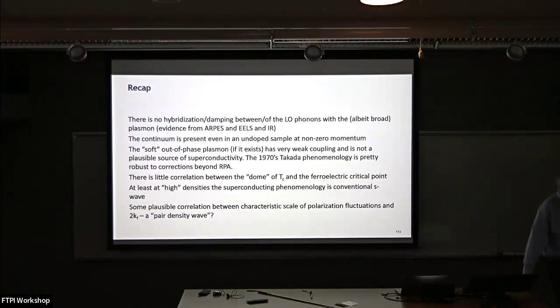Quick question. In the very dilute limit where you have one pocket, what in your mind is the transport scattering mechanism? It looks like an ordinary metal. You have a tiny pocket. Well, here's another conundrum. These are very good metals at low temperature. By the time you hit room temperature, they're very bad metals. That's up to 80, 100 Kelvin. And by the way, there are three materials that do this right now, and they're all on the verge of being ferroelectrics: strontium titanate, potassium tantalate, and tin telluride. They all have basically a T-squared resistivity, so the mobility is dropping very slowly. What's the mechanism for scattering? I don't know. I think that needs to be understood.